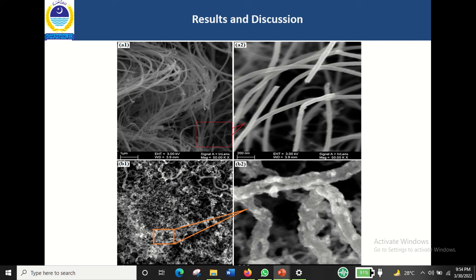It shows fine structures with uniform diameter distribution of the carbon nanotubes. And this uniform distribution of the structures represents that there is a controlled growth of the carbon nanotubes. The bottom left image shows the SEM image of the lanthanum ZnO carbon nanotube photocatalyst, and the right bottom image shows a magnified image of the left one.